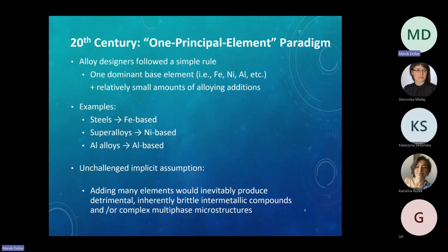Because based on the experience we had, and still have, when you add elements, very quickly you start reaching the point where the stability of the structure, let's say the solid solution form, is a challenge. Inevitably, with a few exceptions, I may mention one of those later on, we produce brittle phases, and they precipitate. So these are particles, and as far as strength is concerned, this is typically a plus. But adding brittle particles, intermetallic compounds, for example nickel aluminum, titanium aluminum, very well-known classes, impacts ductility. And inevitably, the concern is the balance of strength and ductility. That's why pretty much no one talks about multi-element alloys, true multi-element alloys.